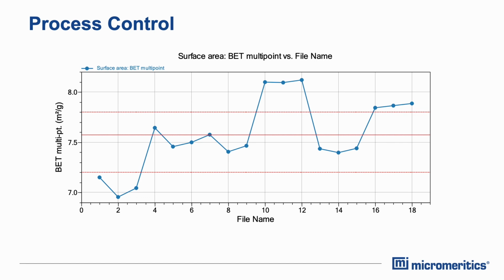The graph that I show here is an example of how BET surface area can be used for process control. To check, for example, how uniformly the coating and calendering process of the electrode went, different pieces from the different positions of the same batch were tested, and we see that they result in quite different surface areas, ranging from around 7 square meters per gram up to over 8 square meters per gram. So this is an easy measurement for process control at this part.